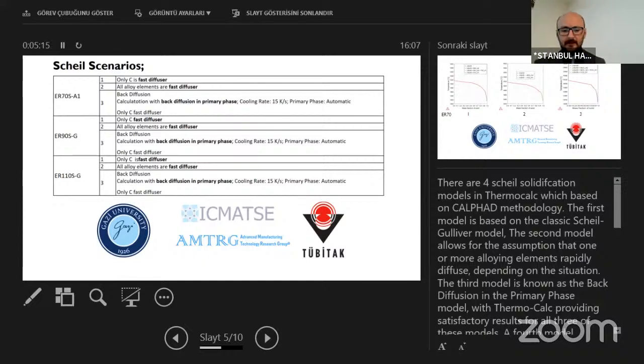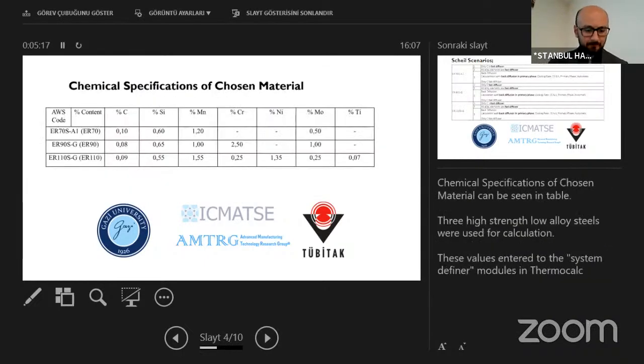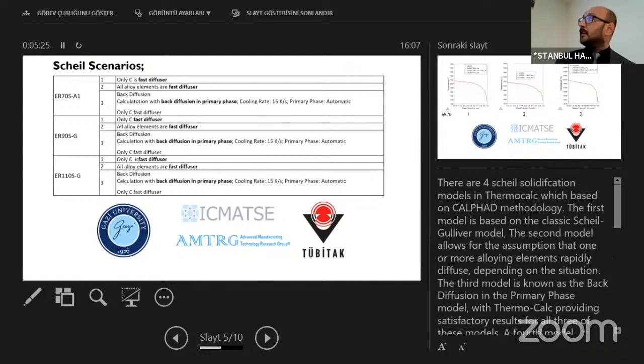and it provides the most accurate results for steel materials. As seen in the previous table, three high-strength low-alloy steels are chosen, each steel employed with three Scheil models. You can see in the table now: the first one is only carbon as fast diffuser, the second one is all alloying elements as fast diffuser, and the third one is back diffusion calculation with primary phase. In this model, cooling rate is 15 Kelvin per second, and the primary phase arrangement is automatic.